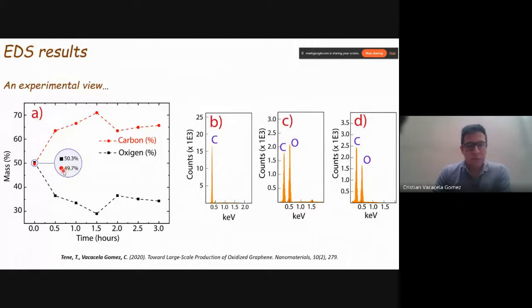But when we apply reductions, for example, as mentioned before, citric acid, hydrazine, and other chemical agents, to reduce the number of oxygen functional groups in our graphene oxide samples, the presence of oxygen starts to decrease. For example, 1.5 hours is the best reduction process. After that, maybe because the reduction is not performed in a controlled way, our material loses oxygen functional groups, but then takes oxygen functional groups from the air again. But here I want to highlight that with increasing reduction time we can reduce the oxygen, which means we are removing the oxygen functional groups from our graphene oxide to prepare reduced graphene oxide.